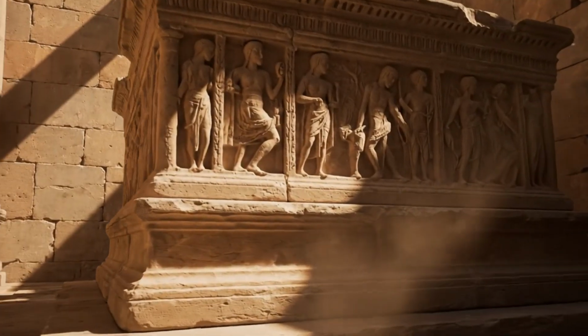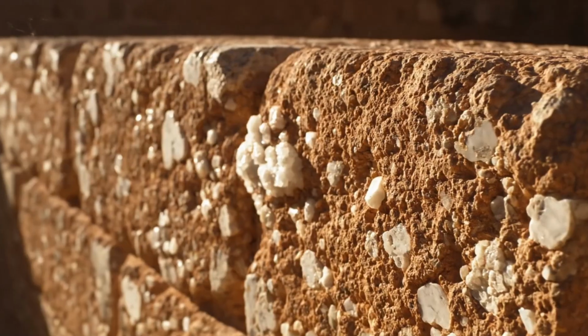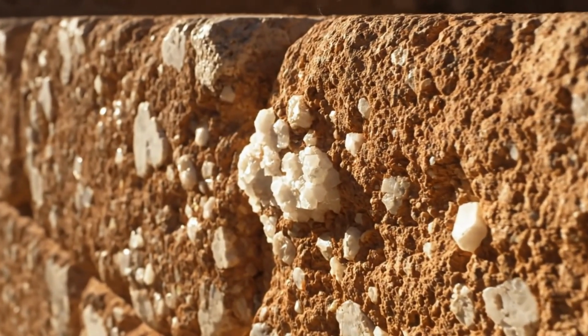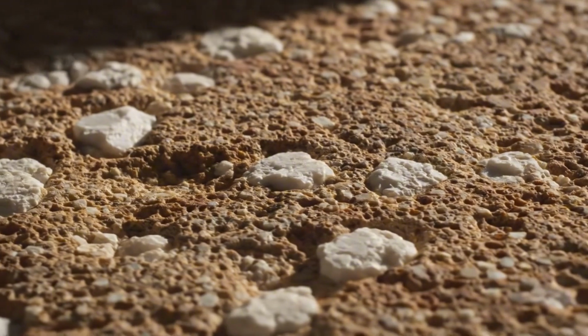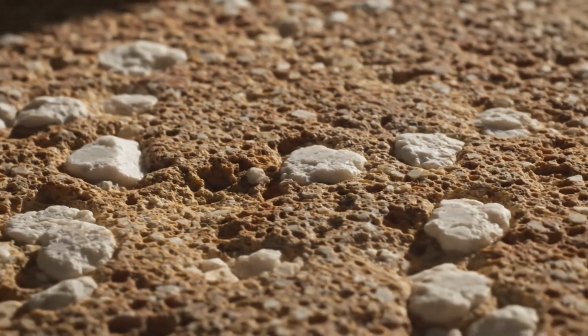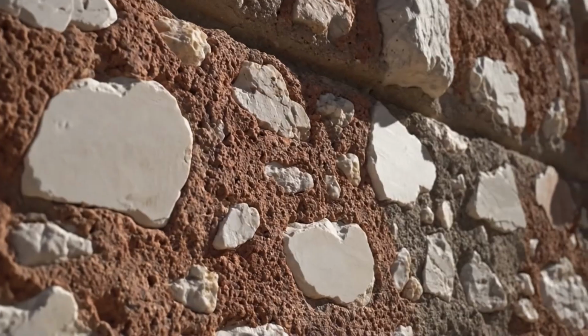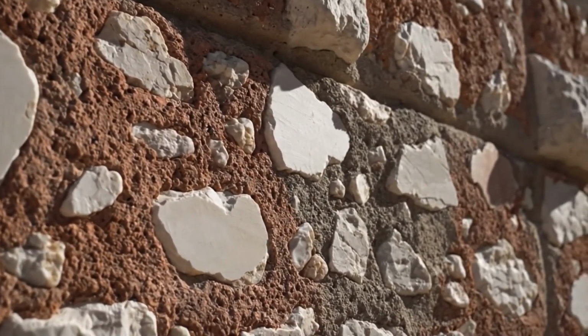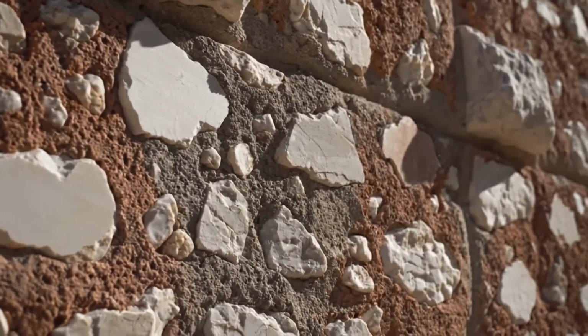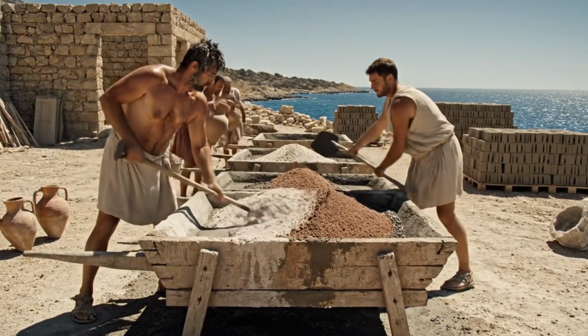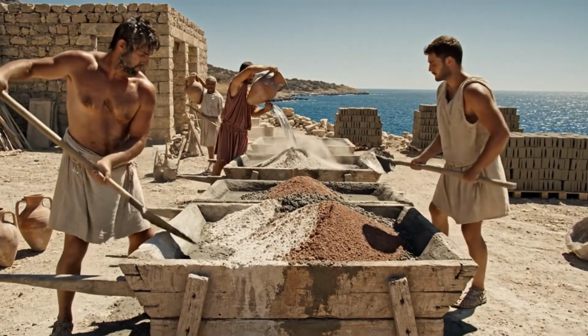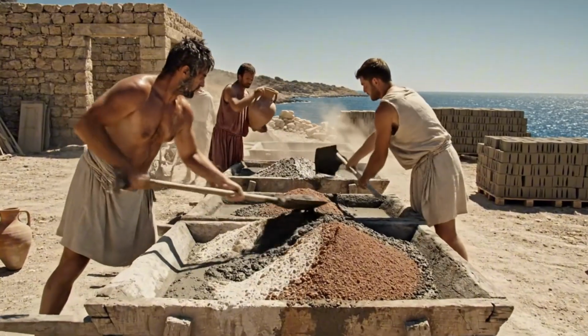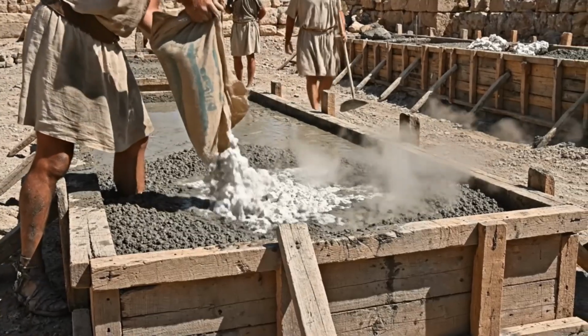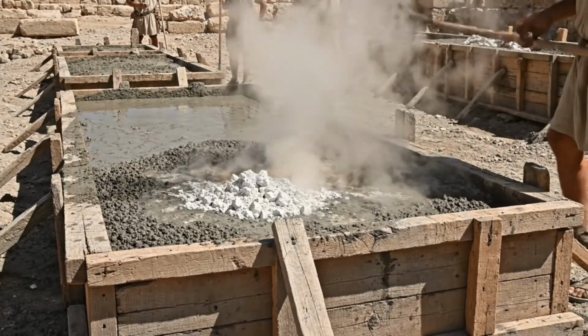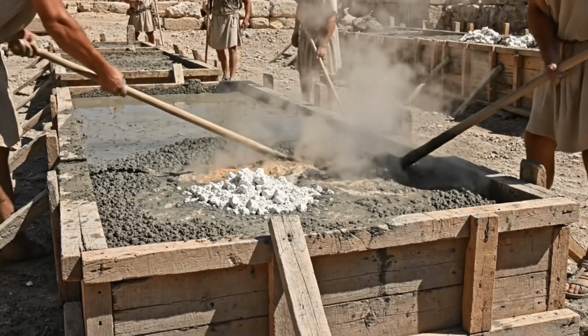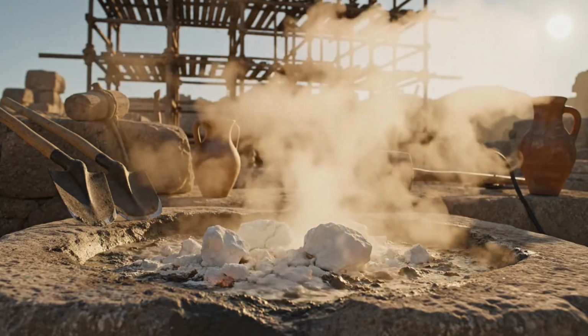The scientific insight emerging from this study is both precise and profound. The durability of this ancient concrete cannot be explained solely by its initial composition. It is the result of chemical processes that continued to unfold long after construction was complete. Through the slow dissolution of leucite and the gradual reconfiguration of the CASH network, the material developed a capacity to reinforce itself over time. In this way, the Tomb of Caecilia Metella stands not only as a relic of Roman ambition, but as evidence of a material system that matured with age, growing more cohesive as the centuries advanced.